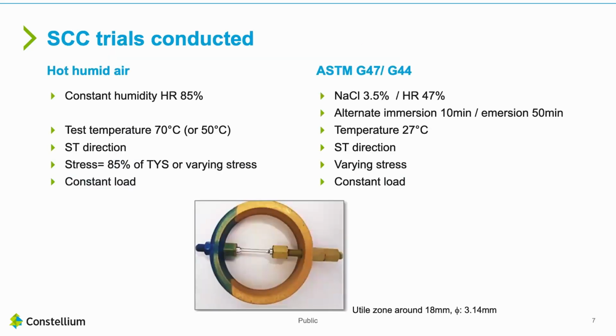For the stress corrosion trial, we have chosen two types of tests. First one is a hot humid air, so metal is put in a constant humidity at 85% of relative humidity. The temperature of the test is quite high at 70 degrees. We also conducted some trials at a lower temperature at 50 degrees.